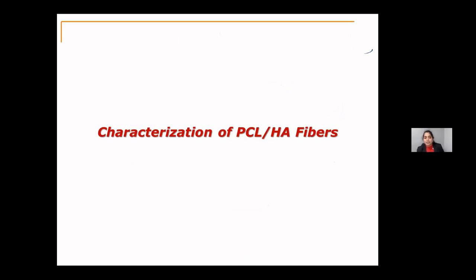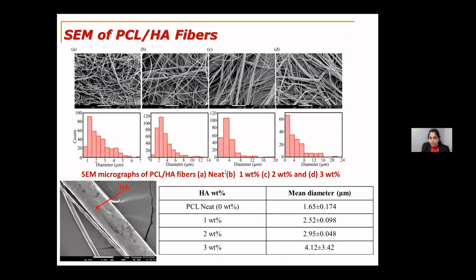Before proceeding to thermal and mechanical testing, we go for the characterization of the PCL hydroxyapatite fibers to check if the fibers were in good shape or not. Here I chose to show 4 samples. The first one is PCL without any hydroxyapatite, only the PCL fibers. And this is the PCL fibers with 1 weight% of hydroxyapatite, this is 2 weight%, and the last one is 3 weight% of hydroxyapatite.